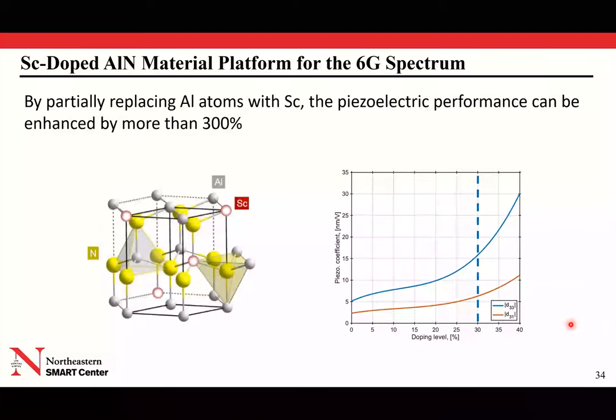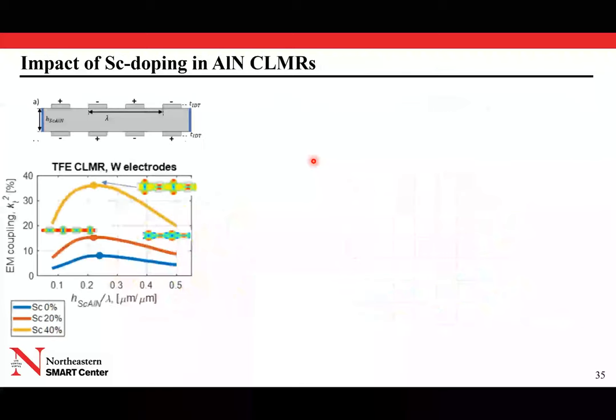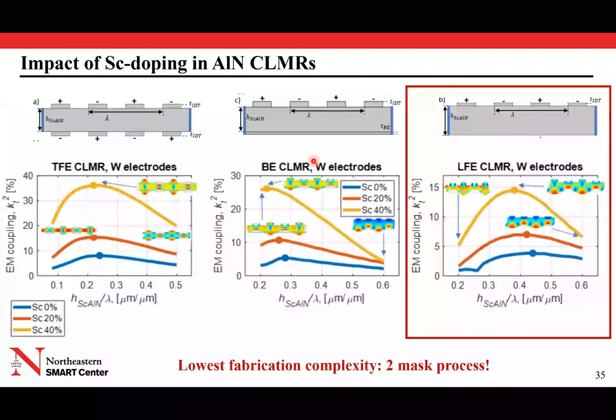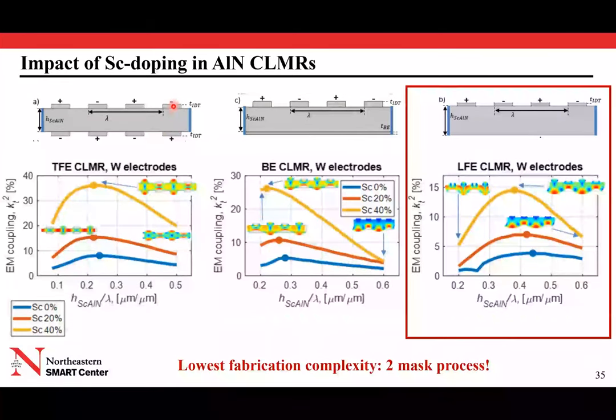So that's one of the things that my group and many other groups in the community have been exploring, like scandium doping of aluminum nitride as a way to increase the coupling coefficients of the material. And you can see here, by doping aluminum nitride with scandium, you can actually increase the coupling d33 and d31 almost by three times, right? And so that's very exciting because that now allows you also to build structures like that cross-sectional Lamé mode resonator that I showed you before, that instead of requiring the top and bottom electrode pattern, can be just implemented with a top electrode because the coupling coefficient of the material now is high enough to support that, and simplifies dramatically the fabrication process of this structure. So we're talking potentially like a two-mask fabrication process to build these devices.